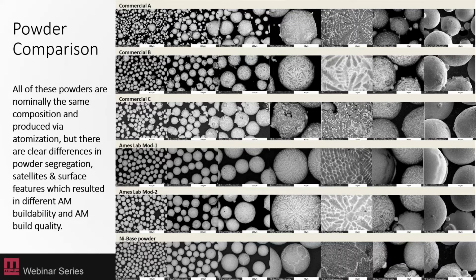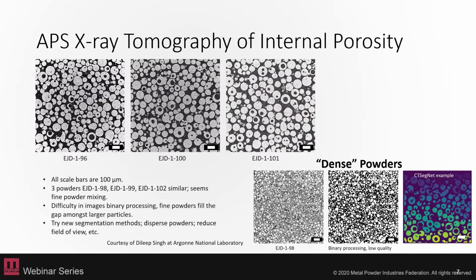Another thing that Amy mentioned is internal porosity of the powders and how that is tracked in the AM builds through the build process, and that the porosity that's initially present in the powders is not eliminated during the AM build because of the violent convection in the melt pool. So these are things that you can't see just by looking on the outside of your powders. These are features that are trapped on the inside. In this case, these are some powders that have been looked at by Dileep Singh at Argonne National Laboratory using the Advanced Photon Source.